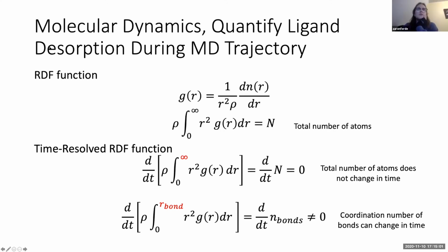Yeah, so you considered the number within a certain radial distance. So with the change of radius, what's the change in the number of species within that incremental change? Okay, and if you take the derivative over distance, it will be the number of neighbors on a certain sphere, right?